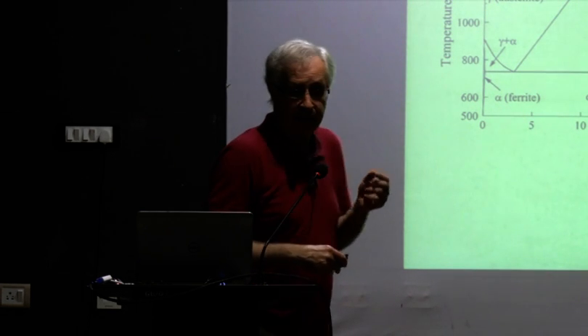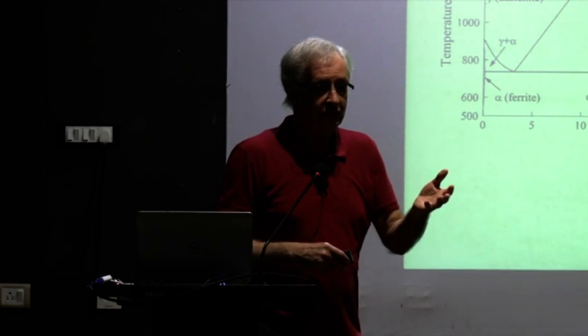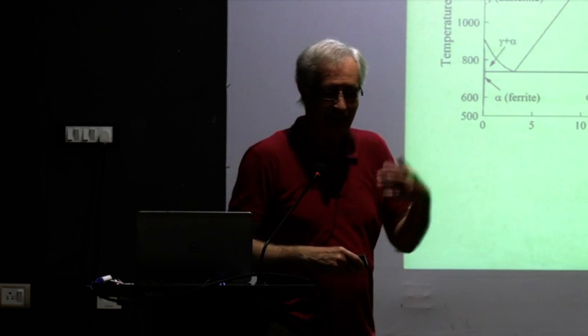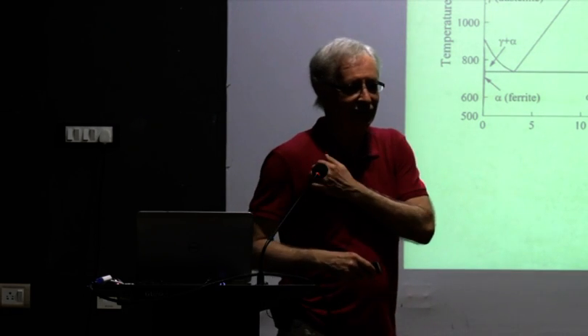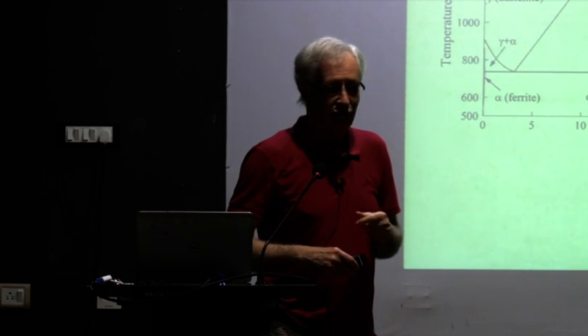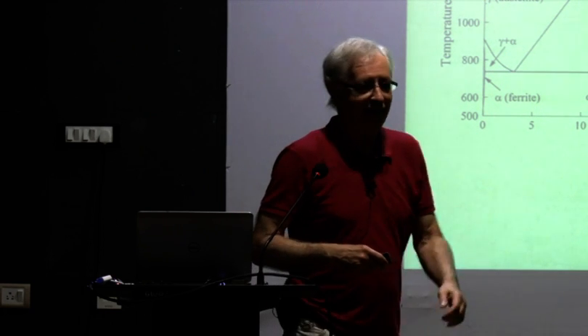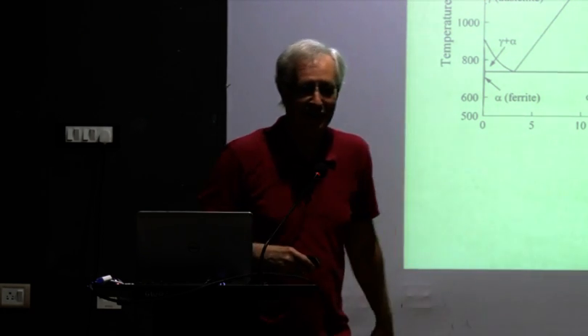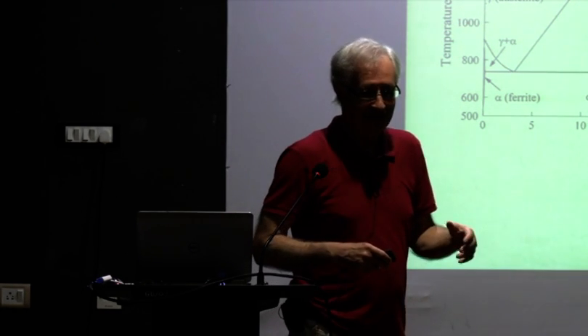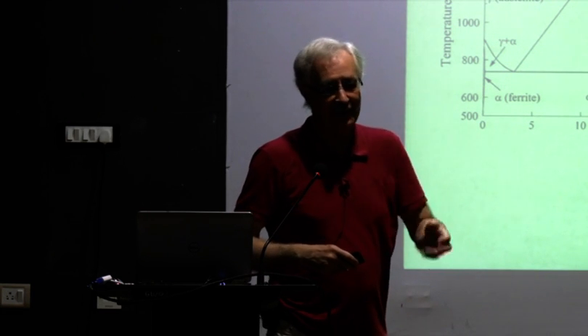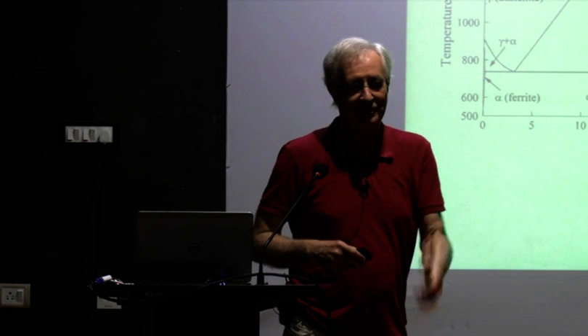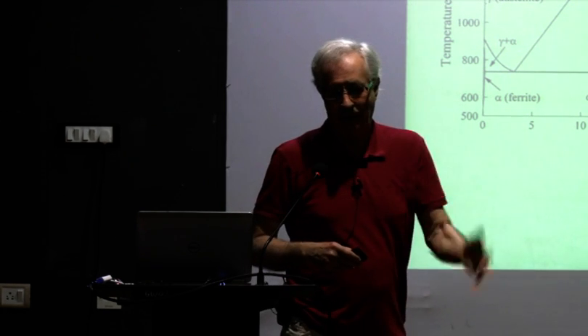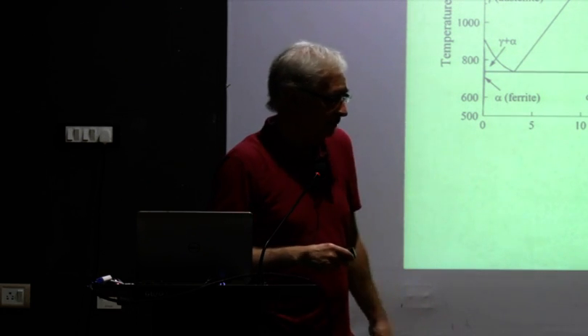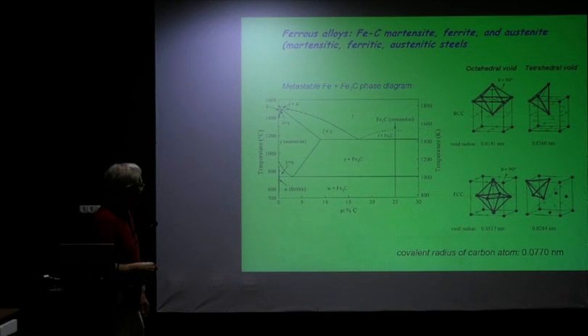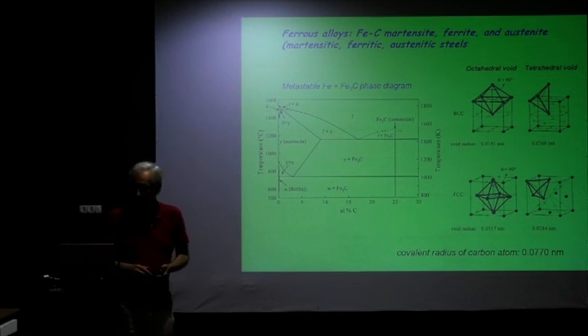Now, the austenitic steels, the typical ones you have in your kitchen, it's called the 18-10 or whatever. It's an iron nickel chromium steel of some sort, and it's face-centered cubic. If you hold a magnet to your kitchen appliances, it should not attract. If it attracts, then it's not of good quality. Okay, it should be non-magnetic. The ferritic steels are ferromagnetic. So that's one way of distinguishing, more or less. It's not in all cases that austenitic steels are non-magnetic, but you can tell whether you have a ferritic steel or an austenitic steel. And then when you come into these regions, you have cementite and things like that. We'll talk about that later on.